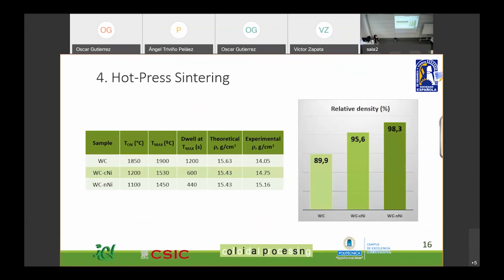So in terms of density, we could also appreciate there are huge differences between them, achieving even less than 90% in the case of binderless tungsten carbide. But in the case, for example, of the use of this nanonickel synthesized by us in our lab, this would be even higher than 98%, which is very good news, actually.